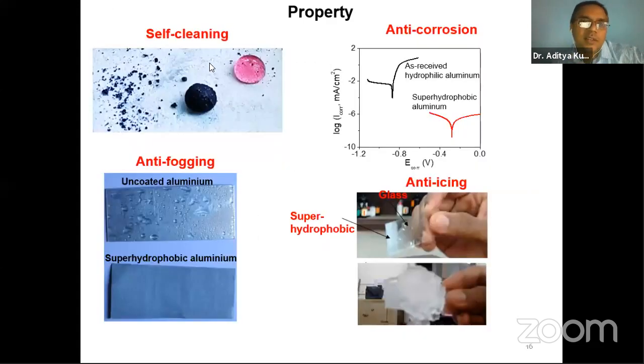So as I said, this has the self-cleaning property. Here you can see a super hydrophobic surface. It makes a spherical bead shape of the water drop. This is colored water, and these are the dirt. The colored water takes all the dirt, and while rolling, the water drop comes off the surface, and your surface will be clean. Anti-fogging. Here in this example, we have an uncoated aluminum surface. This is a super hydrophobic aluminum surface.